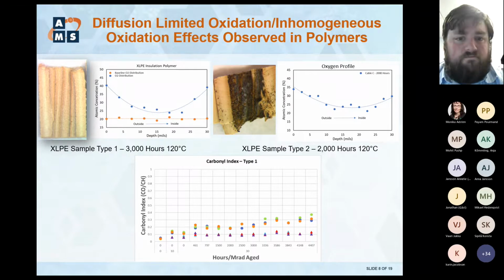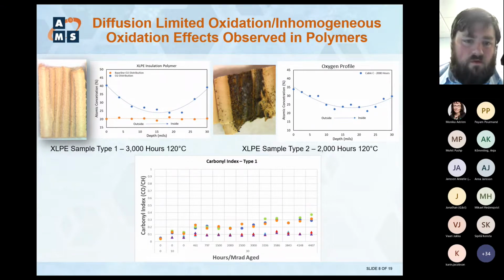So that's the idea behind the type 1s. Type 1s have DLO effects, but type 2s and type 3s may have even more significant inhomogeneous effects. In our radiation and thermal studies we're doing right now, we're doing FTIR profiling. So we're actually microtoming through the insulation. The XLPE, this is a cross-linked polyethylene at different thermal aging hours.